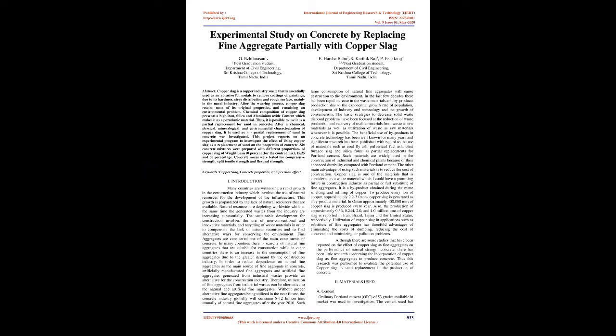Copper slag is one of the materials that is considered a waste material, which could have a promising future in the construction industry as a partial or full substitute of fine aggregates. It is a byproduct obtained during the matte smelting and refining of copper. To produce every ton of copper, approximately 2.2 to 3.0 tons of copper slag is generated as a byproduct material. In Oman approximately 400,000 tons of copper slag is produced every year. Also, the production of approximately 0.36, 0.244, 2.0, and 4.0 million tons of copper slag is reported in Iran, Brazil, Japan and the United States, respectively.